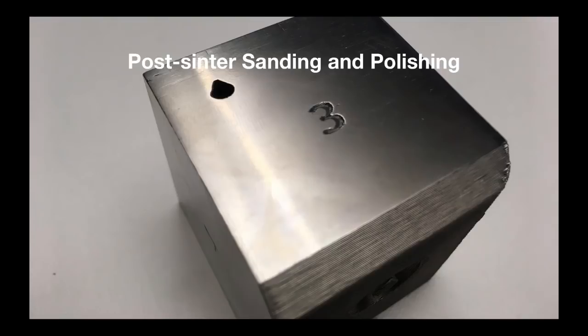And then we have some tool steels coming out. Probably the first one will come out as H13 down the road a little bit, and that I believe can get up to about 45 or 50 Rockwell, maybe a little bit higher than that. So the nice thing is that when they come out of the furnace, they will be in that as-sintered state, so they'll be a little bit softer and a little bit easier to work with, but it's still going to be a lot more effort to sand and polish a part like that than it would be in the green state. So that's one of the trade-offs there.